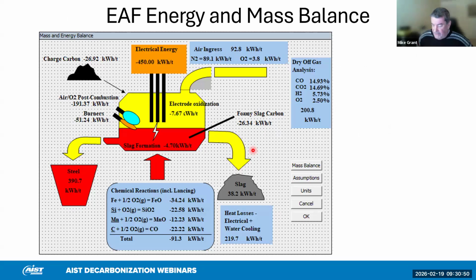Just a quick energy balance. We categorize the electric arc furnace by how much power it uses. A typical electrical energy consumption is about 450 kilowatt hours per ton. And this is the amount that determines the productivity of the electric arc furnace. How fast we can deliver that electricity determines the speed at which we can produce a batch of steel. Other energy contributors, though, are the reactions involving oxygen.